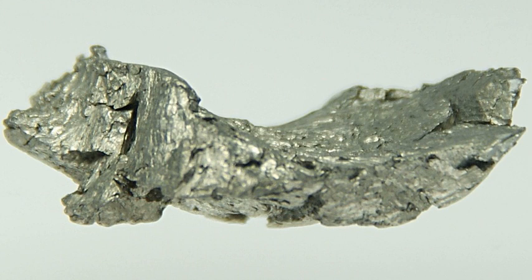Gadolinium metal is obtained from its oxide or salts by heating it with calcium at 1450 degrees Celsius in an argon atmosphere. Sponge gadolinium can be produced by reducing molten GdCl3 with an appropriate metal at temperatures below 1312 degrees Celsius, the melting point of Gd, at a reduced pressure.